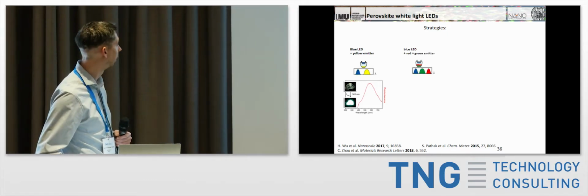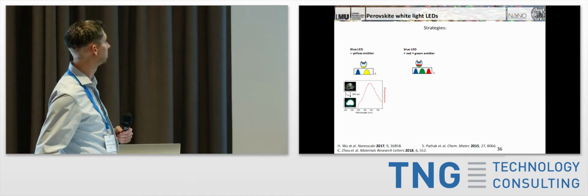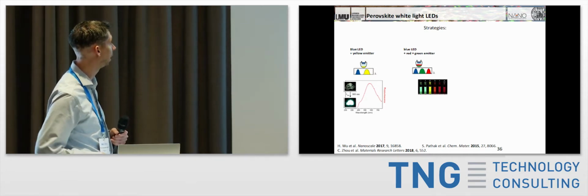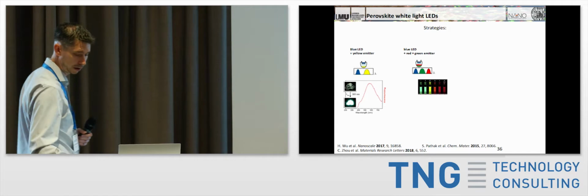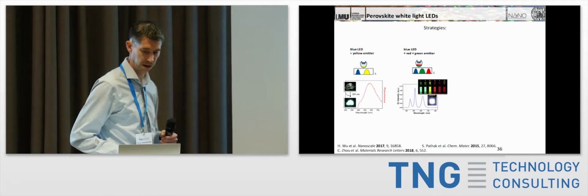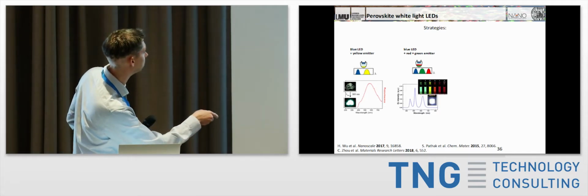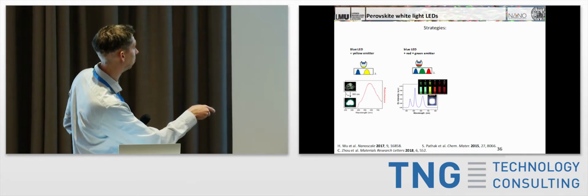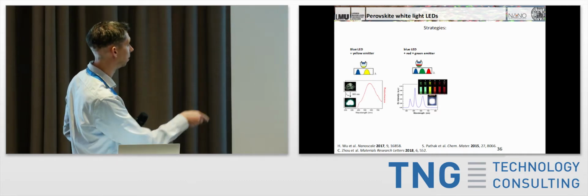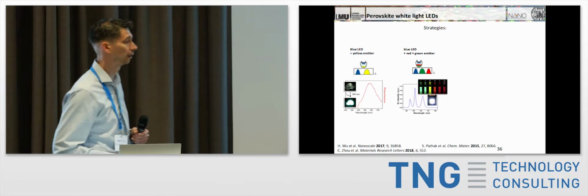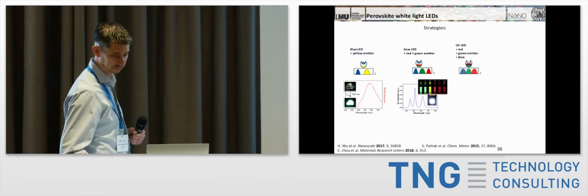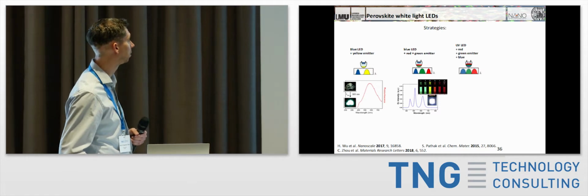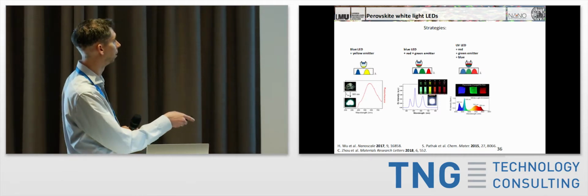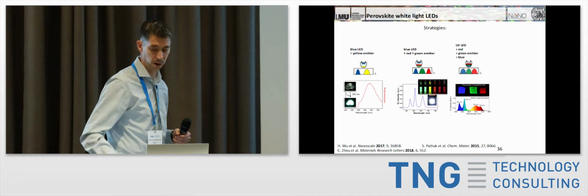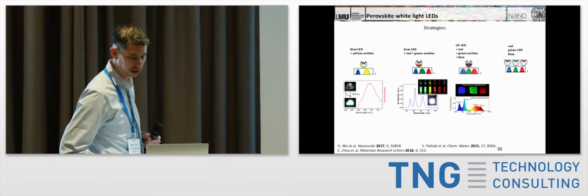You can also tune the perovskites to be red and green emitters, absorbing the blue light to get white light out of there. There are also people that have made LEDs there. Essentially this is the light from the blue LED that's on the back, and then the green and the red perovskites add up to make white light. Going further, basically producing something in the UV so that all of the emitters are now perovskites. So you have a blue and a green and a red perovskite adding up to make white light as well, as you do in a typical TV.